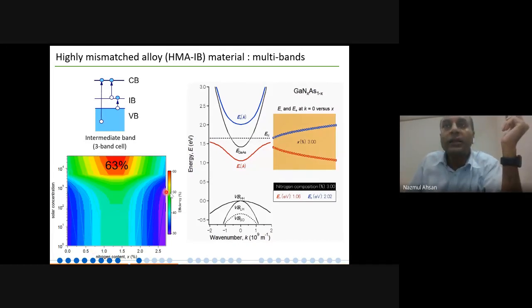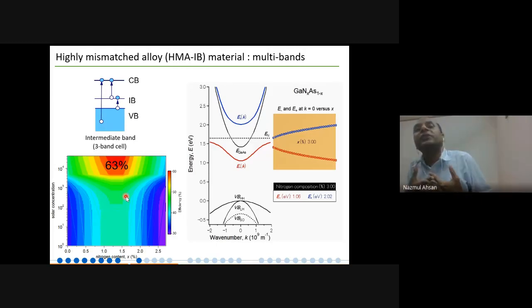And this is my picture, and this color tells the conversion efficiency. If you have 0%, you are very close to the green area, and the green area means somewhere around 30%. But if you increase the nitrogen concentration, let's say 1%, then you do have 3 band gaps like this, and in that case, under one sun, your solar cell efficiency will be close to 40%. But if you increase the solar concentration, going higher and higher, the highest is the red area, and there you can make a solar cell of 63%. This number is very close to 1% of nitrogen, under a concentration of 10,000 times. So this is the benefit of concentration.